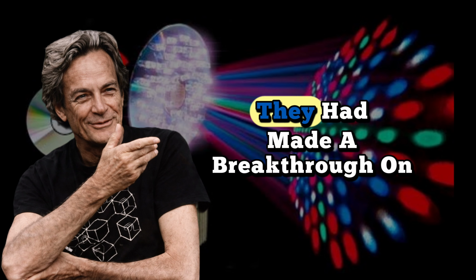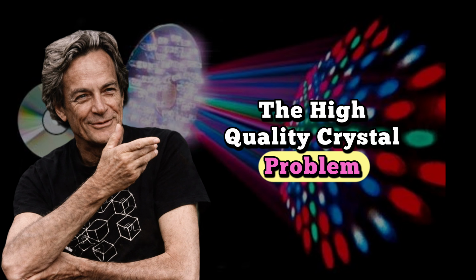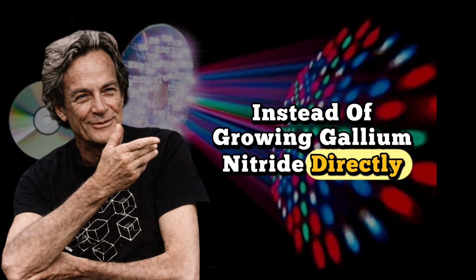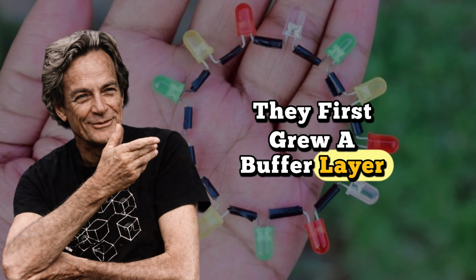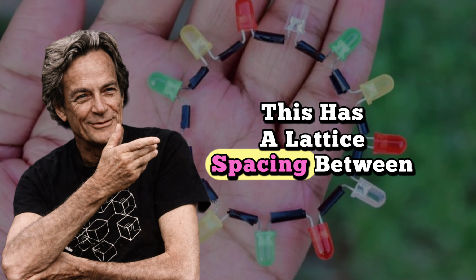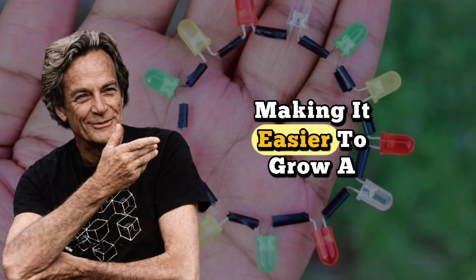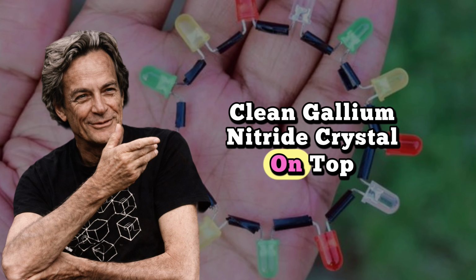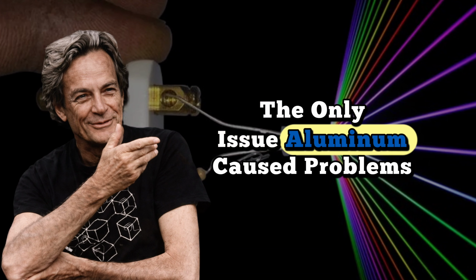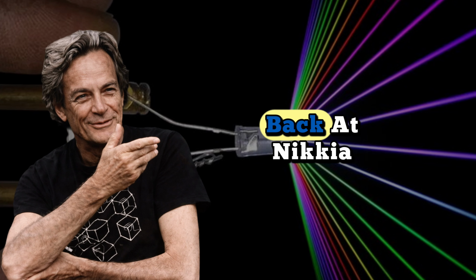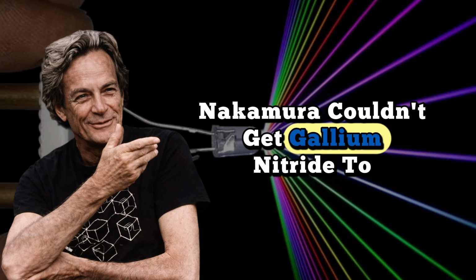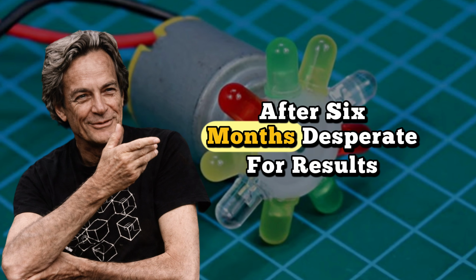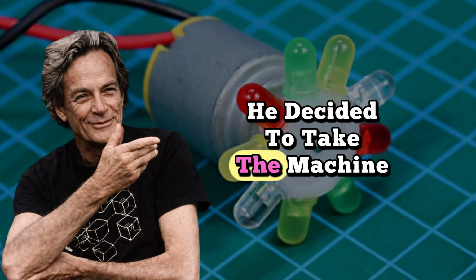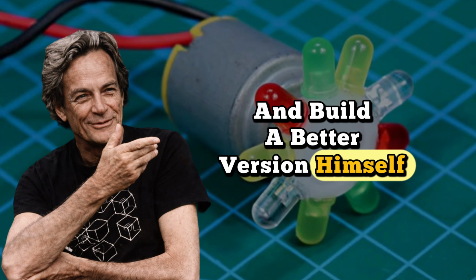A few years earlier, they had made a breakthrough on the high-quality crystal problem. Instead of growing gallium nitride directly on sapphire, they first grew a buffer layer of aluminum nitride. This has a lattice spacing between the other two materials, making it easier to grow a clean gallium nitride crystal on top. The only issue, aluminum caused problems for the MOCVD reactor, making the process hard to scale. Back at Nichia, Nakamura couldn't get gallium nitride to even grow normally in his new MOCVD reactor. After 6 months, desperate for results, he decided to take the machine apart and build a better version himself.